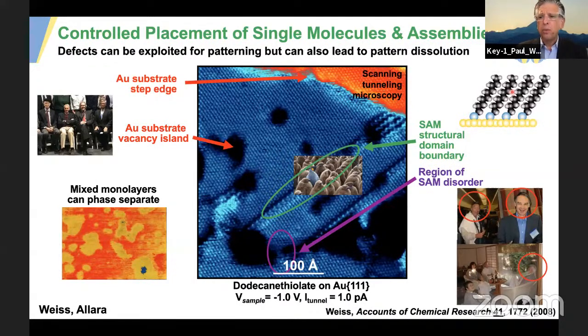And at the time, it was thought the molecules went down randomly and irreversibly and were immobile once they were on the surface. But even before we got molecular resolution, our very first images of these layers showed that all those three ideas were wrong, that the molecules were dynamic on the surface, that they phase separated, that over time they reduced the interface length because that was unfavorable, the cross interactions for these two different terminal functional groups.